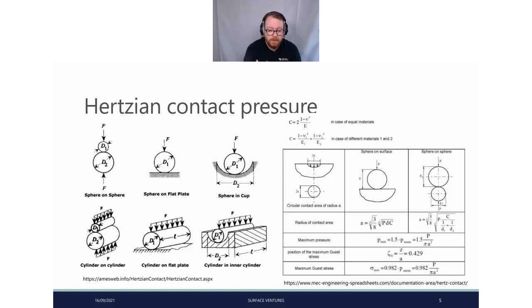Of course, with this we have a specific contact radius, something that when you are setting up a fretting test, you should always calculate. What is your nominal radius of contact? Of course, this is going to change during the test, but it's something you should be aware of. And one of the most important things is what is your maximum Hertzian contact pressure relative to your contact radius and the type of geometry that you're using, because this really sets up how well your test is going to mimic what you're actually modeling.